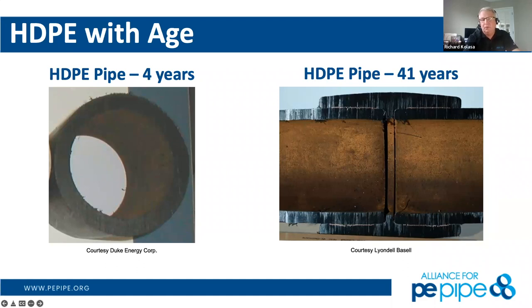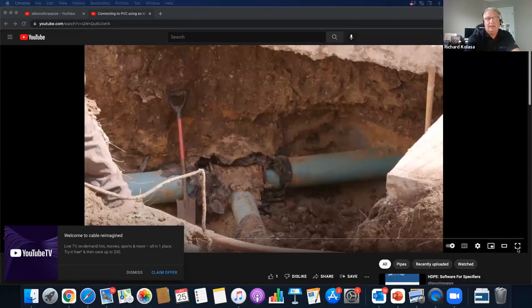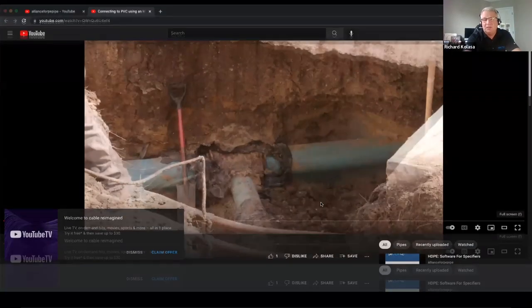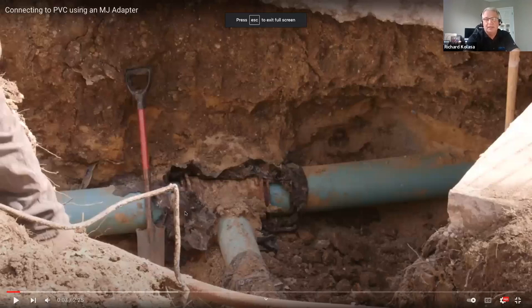So when we had the polyethylene tubes in Nevada and the Las Vegas area, coming up the sides of these houses because they don't have basements, the west side and south-facing tubes that were exposed were very, very warm. They got up to 180 degrees Fahrenheit, which made chlorine very, very active. So it affected that slow crack growth performance of the polyethylene. It was a real learning tool for us because it was the second generation polyethylenes being used at that time, and they failed. They had little pinhole failures, which are classic slow crack growth type failures.